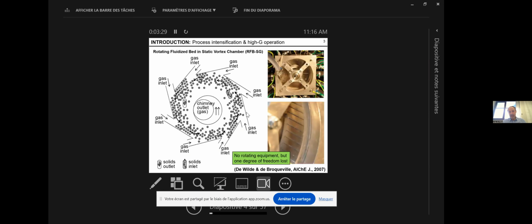For coating, this is work we've done with Campina. We were asked to coat cohesive powders, and did that in a vortex chamber. Let me explain here the functioning of the vortex chamber. You introduce gas or liquid tangentially. And so the entire device is static, but the motion in the chamber is rotational. Yeah? And the fluid is evacuated centrally here. And of course, if you suspend particles in such a rotating motion due to their inertia, what they call the centrifugal force, but it's inertia, they accumulate near the wall and they are glued against the wall, so they rotate against the wall. Yeah?